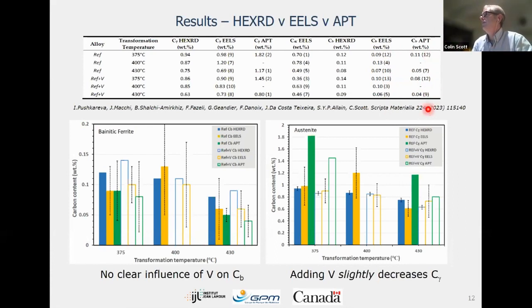If we look at the trends, look at bainitic ferrite first. So we've got the carbon content against the transformation temperature. The solid curves here, the solid blocks here, if you like, are from the reference steel, and the open ones are from the vanadium steel.